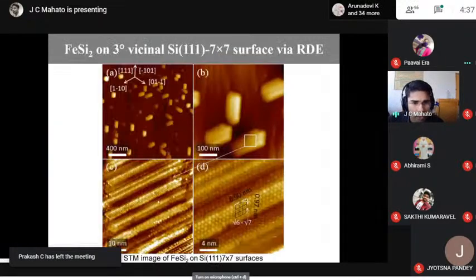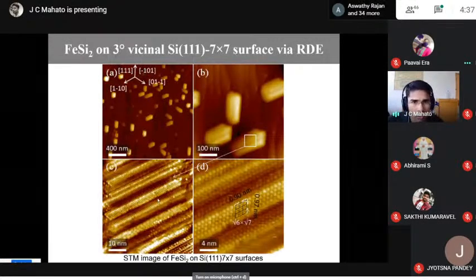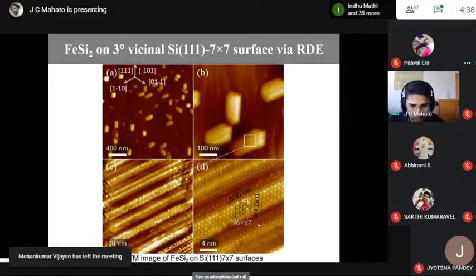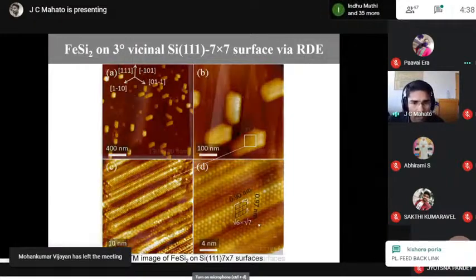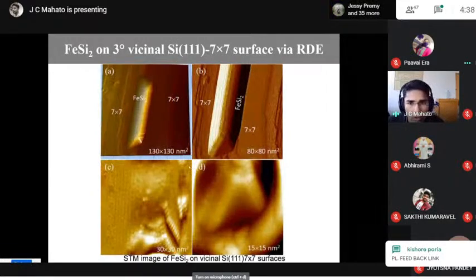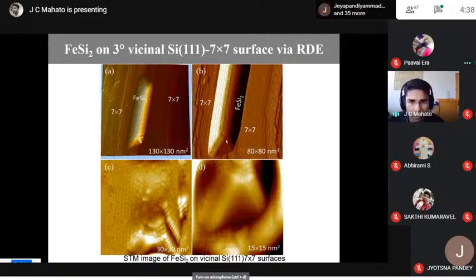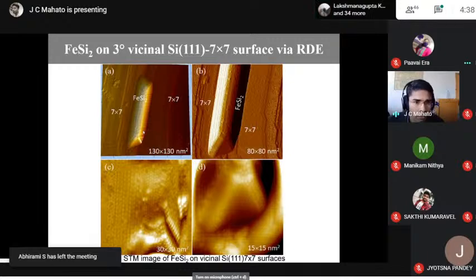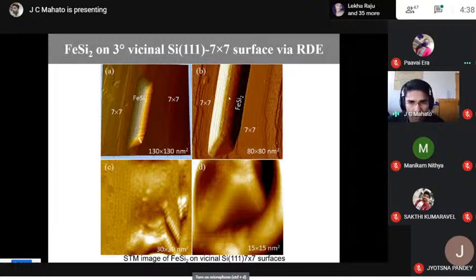So this is the STM image of the iron silicide grown nanostructure on the silicon 111 vicinal surface. We found that the iron silicide grows as a nanodot or a nanorod or nanowire, and we could see that the top surface is a new reconstruction, and the primitive unit of this is root 7 by root 6. This is another image of the iron silicide grown nanostructure, and here we clearly see that the iron disilicide nanowires actually have distinct facets, 4 distinct sidewall facets, and a top flat surface of 4 to 5 atomic separation wide.